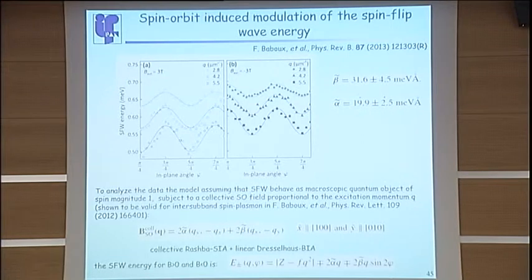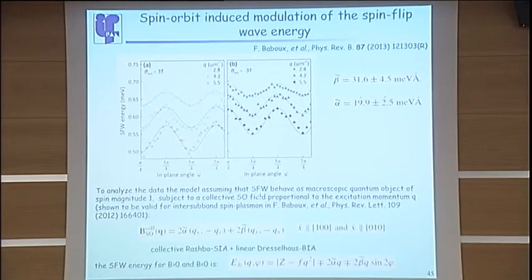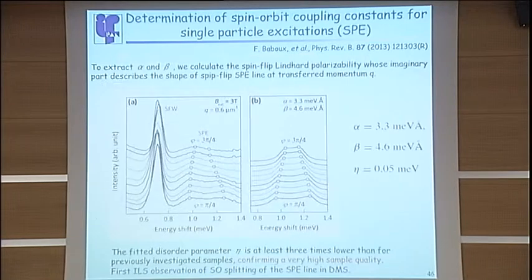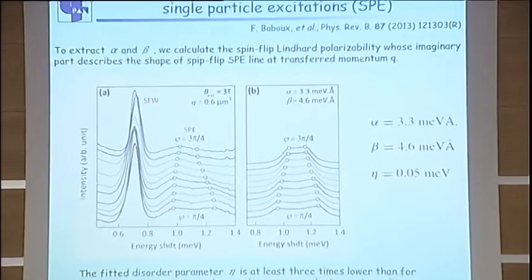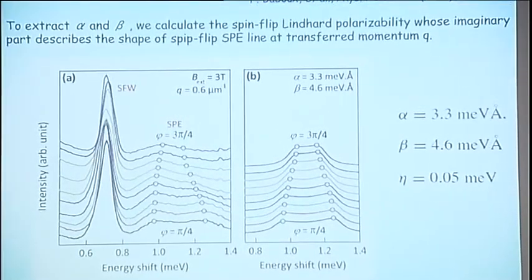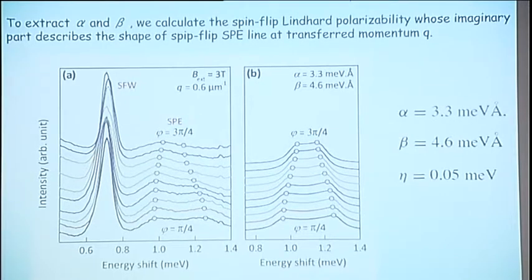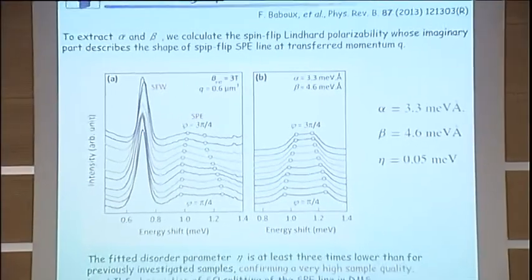In the model they have assumed the same as in the previous paper, that the spin flip wave can be treated as a macroscopic object subject to the collective spin excitation, proportional to this excitation. So using this formula, they were able to reproduce data quite well. Also, in order to determine the alpha and beta at single particle level, they had to produce some calculation of polarizability, but with this type of parameter, they were able to describe data reasonably well.